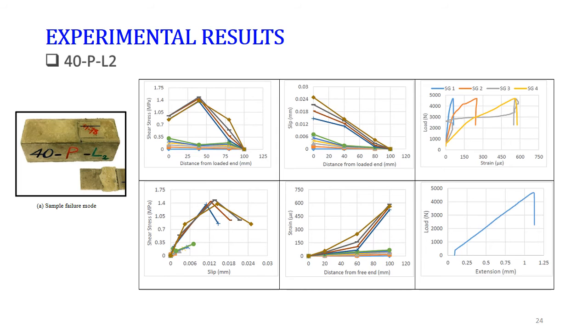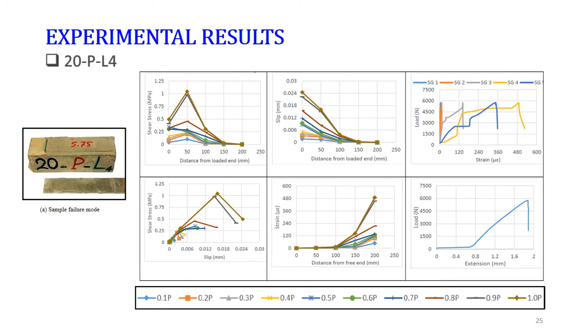So you can see how the behavior changes as the length changes, and as the material strength of the concrete also changes. The last one is for an even lower strength, 20 megapascal, and the length is L4, which is the bonded length. And you can see the different curves that are shown for the stress versus distance, stress versus slip, load versus extension, load versus strain, and so forth.